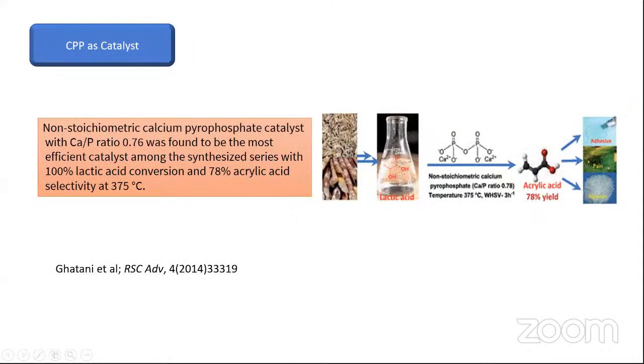We are coming to the application part of calcium pyrophosphate. Now, the popular application is, as usual, catalysis. A non-stoichiometric calcium pyrophosphate catalyst with a calcium to phosphorus ratio of 0.76 was found to be the most efficient catalyst among the synthesized series, with 100% lactic acid conversion and 78% acrylic acid selectivity at 375 degrees Celsius. So it is used for lactic acid and acrylic acid conversion. There are many more examples, but I have selected one example.